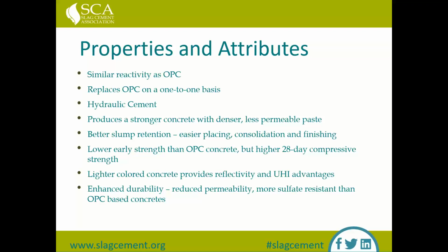Typically with the slag cement mix, you're going to see lower early strengths than with an ordinary Portland cement, but at least equal or higher 28-day compressive strengths typically. Several variables involved in that process, but generally speaking, slag is going to perform better down the line, even extending this to 56 days or possibly even 90 days, depending on replacement levels.